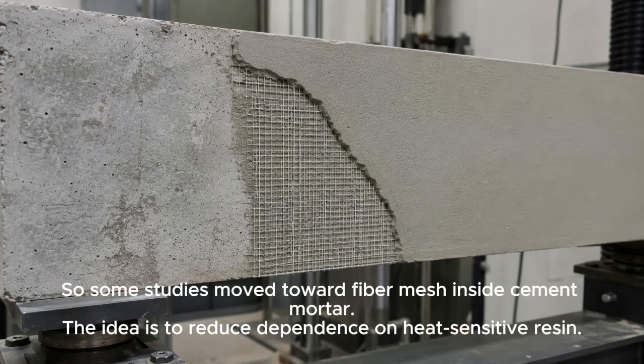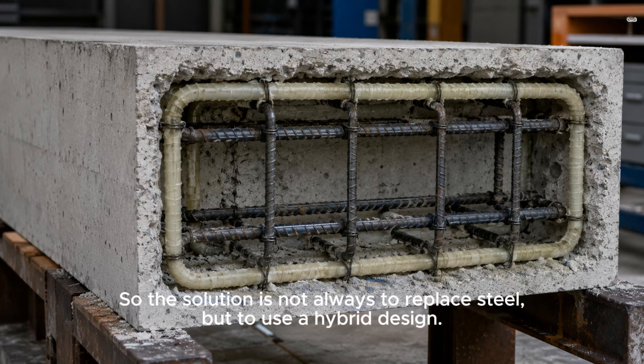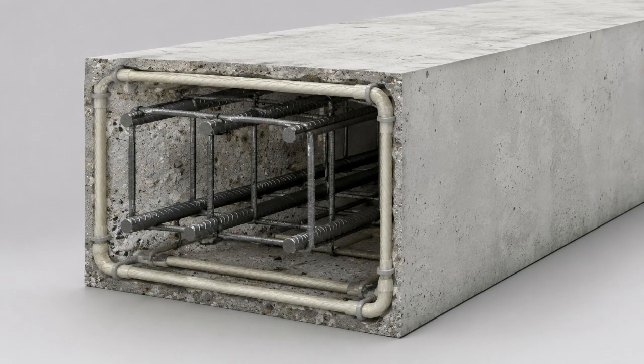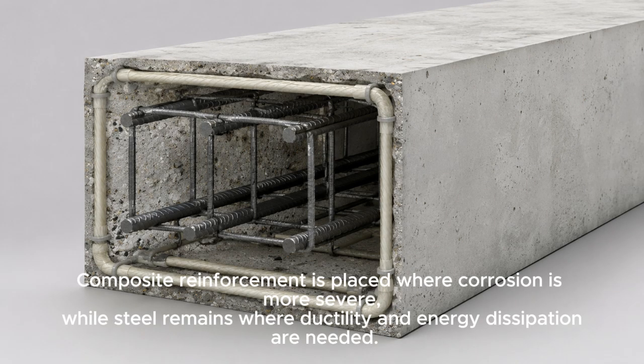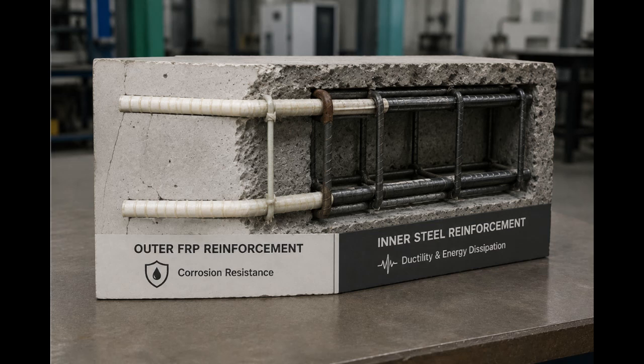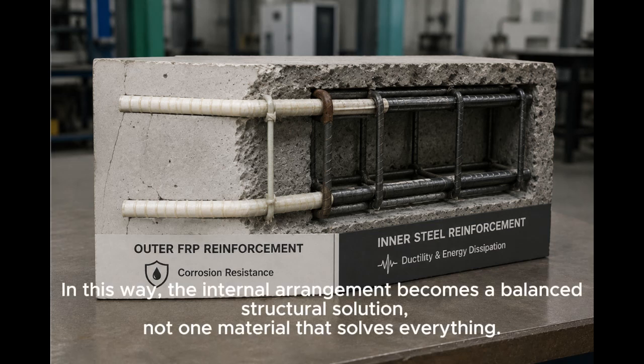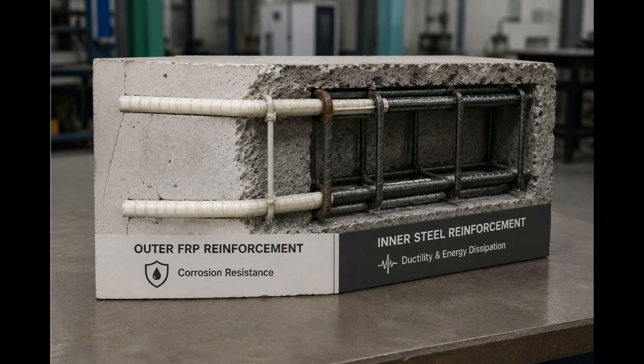So some studies move toward fiber mesh inside cement mortar. The idea is to reduce dependence on heat-sensitive resin. So the solution is not always to replace steel, but to use a hybrid design. Composite reinforcement is placed where corrosion is more severe, while steel remains where ductility and energy dissipation are needed. In this way, the internal arrangement becomes a balanced structural solution, not one material that solves everything.